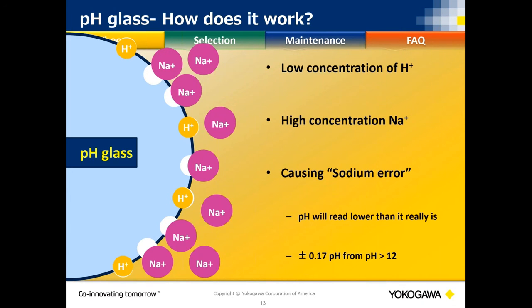it's an acid. So you actually will read what we call sodium error in, say, about the 12 to 14 pH range. You may see this, where your equipment will read 0.17 pH off. Because it thinks of it as an acid, it'll actually read low all the time. It'll read 0.17 pH low. And it doesn't matter whose equipment it is, this is still an anomaly across the board in pH measurement. It's just one of the things that you have to deal with when you talk about pH: sodium errors in the caustic range, like I said, about that 12 to 14 pH range.